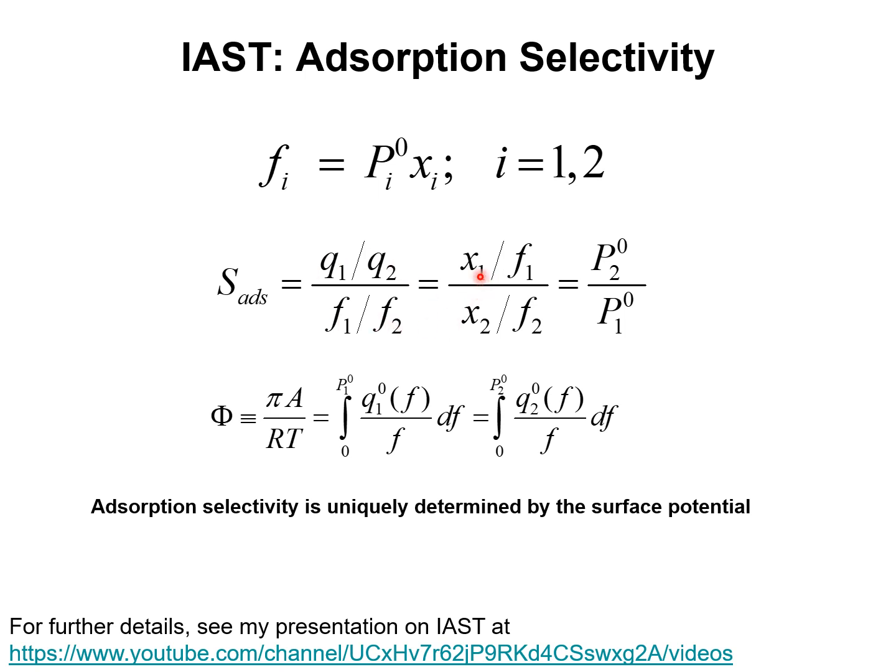This expression may be rewritten in terms of the mole fractions, x1 and x2. In view of this expression relating the partial fugacities, sorption pressures and mole fractions, we write the adsorption selectivity of 1 with respect to 2 as the ratio of the sorption pressure of 2 with respect to the sorption pressure of 1.